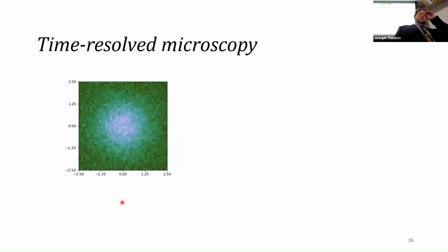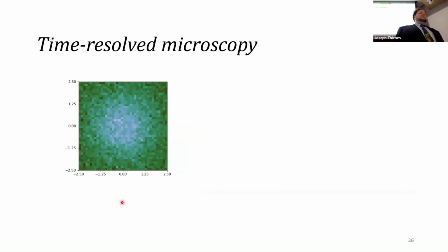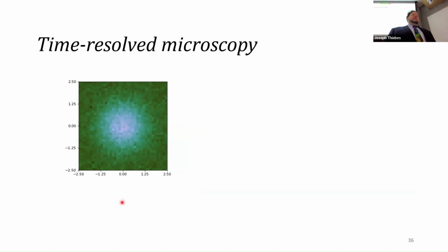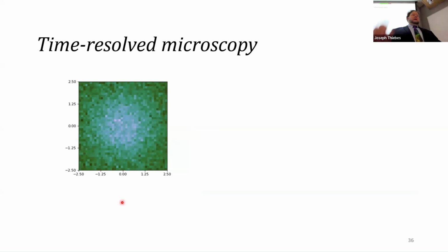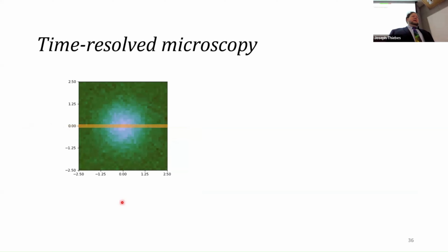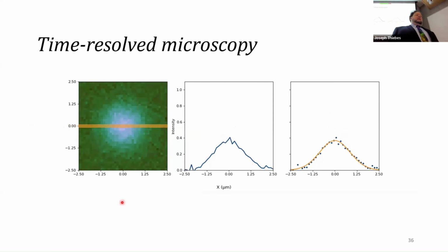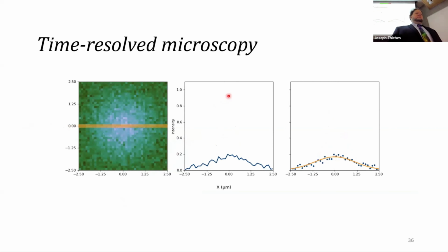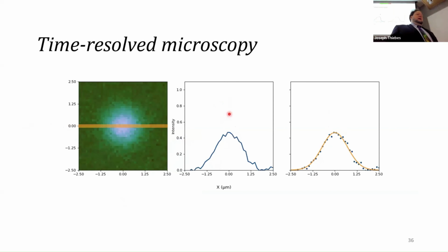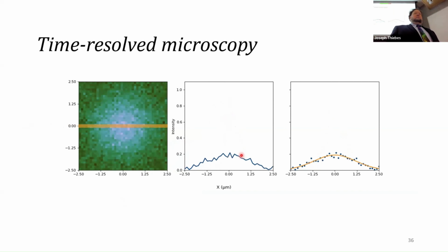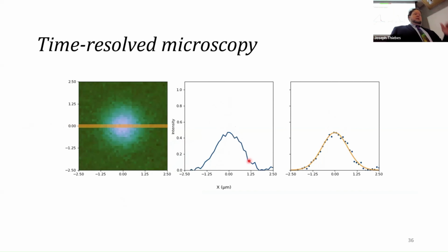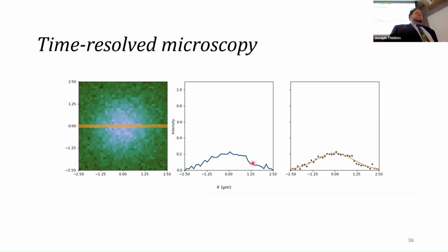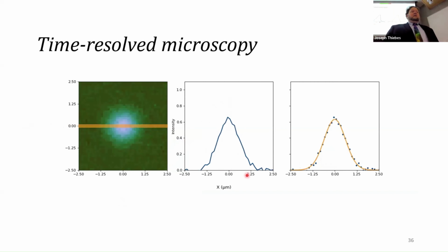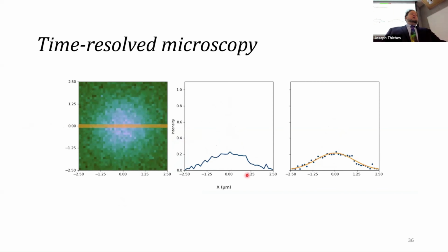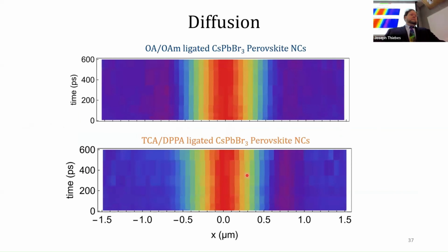So just to recap quickly before I get into how we looked at this time-resolved microscopy, we've got this movie where we see the excited state population diffusing out. And we can take a cross-section of that, or we can also integrate it in one dimension. And we can see that basically the height of these peaks is the intensity. And over time, that bell curve spreads out and diminishes. And using that, we can calculate how the diffusion is going, how quickly the excited states are moving through the material.